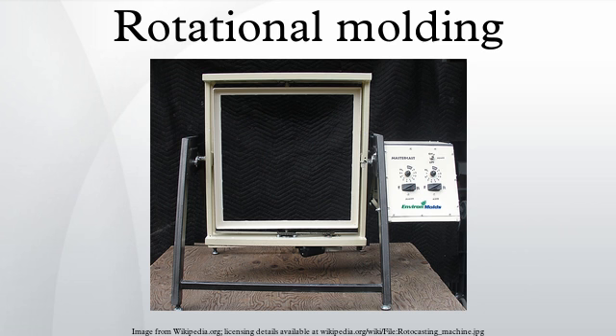Too long and the polymer will degrade, reducing impact strength. If the mold spends too little time in the oven, the polymer melt may be incomplete. The polymer grains will not have time to fully melt and coalesce on the mold wall, resulting in large bubbles in the polymer. This has an adverse effect on the mechanical properties of the finished product.